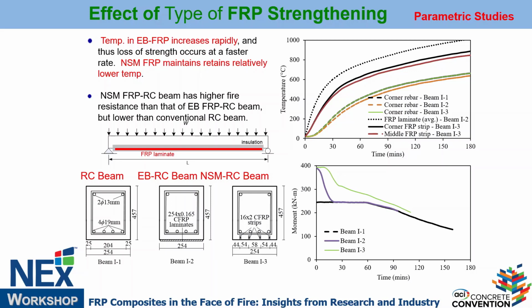kilonewton meters. So nothing happens up to 70-80 minutes in concrete as we expected. So then it starts to lose moment capacity. This is moment capacity. Now if you strengthen it with EB, within 15 minutes or so, glass transition temperature is reached, the strength degrades in FRP, and then it behaves just like a reinforced concrete beam. So the FRP is gone.